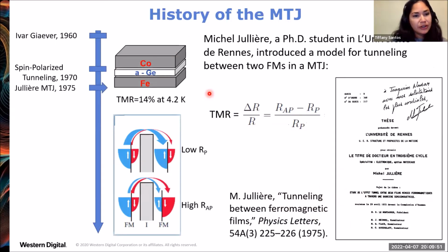And then a few years later, in 1975, Michel Jullière in France, he was a graduate student at the time, and he was inspired by the work of Meservey and Tedrow. He had learned from them that spin is conserved in the tunneling process, and so he proposed tunneling between two ferromagnets across this insulating tunnel barrier. This was the structure that he used. The ferromagnetic electrodes were cobalt and iron, and with a thin tunnel barrier in between. Tunnel barriers are typically 1 to 2 nanometers in thickness. And he proposed this model for tunneling between the two ferromagnets, saying that there should be two stable resistance states. So I will describe how this works.